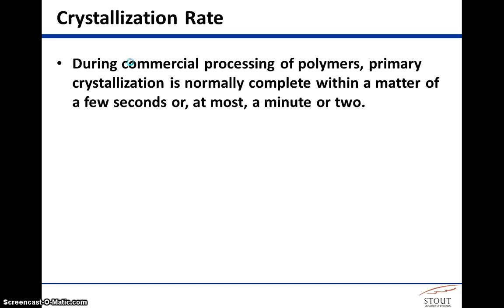Then you're looking at this kind of kinetically hindered snapshot of the orientation that those polymers could achieve. They're trying to achieve the crystalline physical crosslinks that could occur, but because it's cooled too quickly, it can't get there in time. And so the part that you might eject in 20 seconds may not be as strong than if you had increased the mold temperature and held it at a higher temperature for longer, which could allow the full maximum crystal size to form.